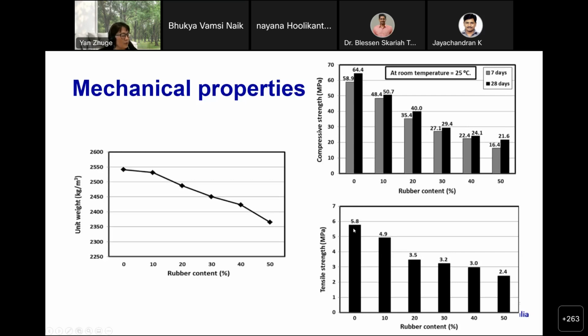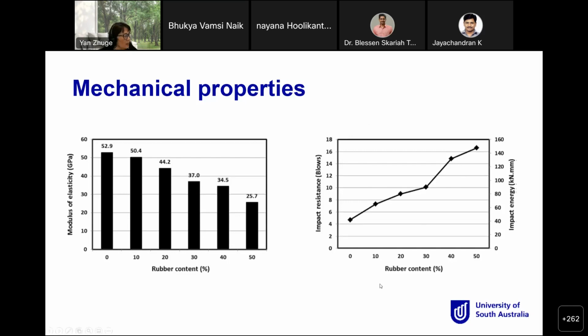This is the tensile strength, which also has a reduction. But as I said earlier, although the flexural strength probably reduced, if you really test the samples of concrete slab, we found there's no reduction at all for the flexural strength. So that is the modulus of elasticity. Of course, it's reduced as well. It's not as significant as the compressive strength, but there is a reduction.